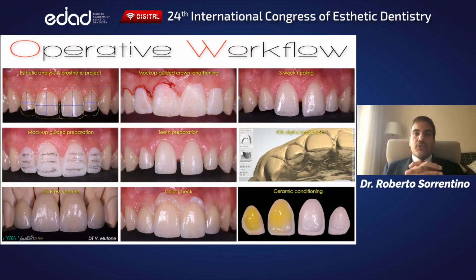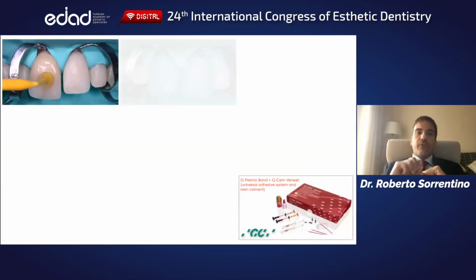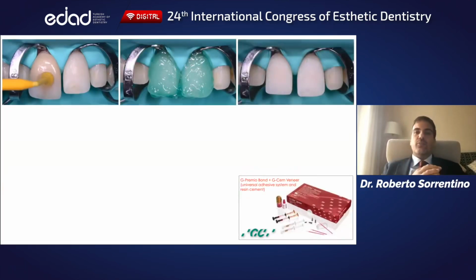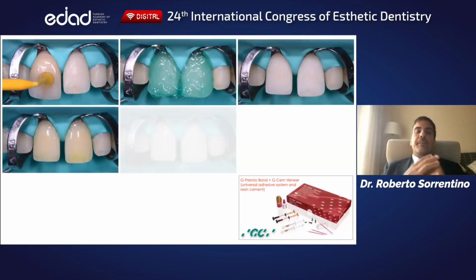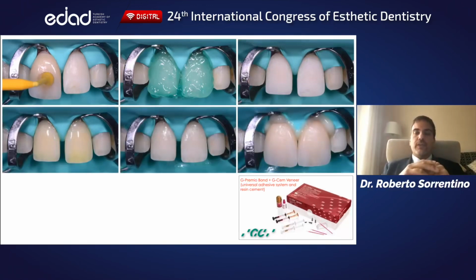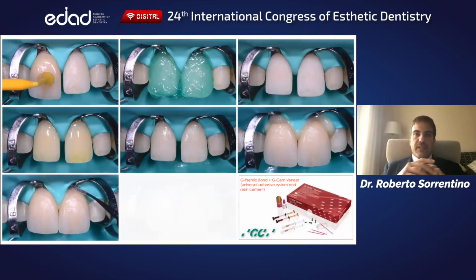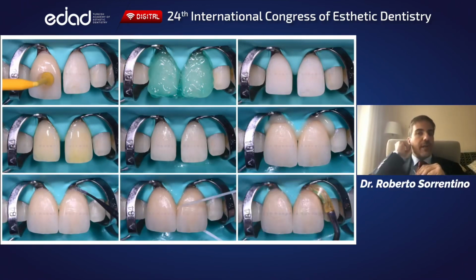After color check, I prepared the ceramic surface for adhesion as previously mentioned. As I was on front maxillary teeth and the veneers were made of glass ceramics, my choice was a total etch approach with a universal adhesive resin cement, namely G-Premio Bond and G-CEM Veneer by GC, a very versatile product in my opinion. Consequently, the use of the rubber dam to isolate the operative field and prevent surface contamination was mandatory, as it was a standard and very easy clinical situation.